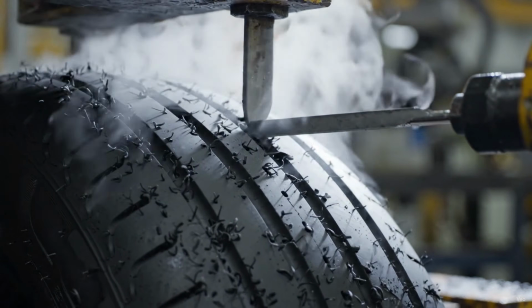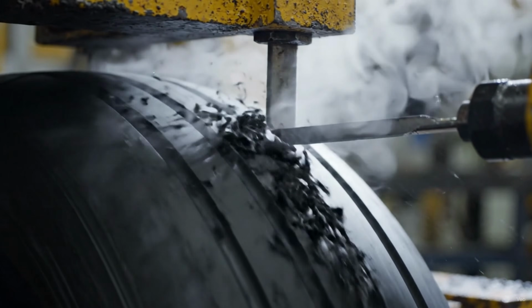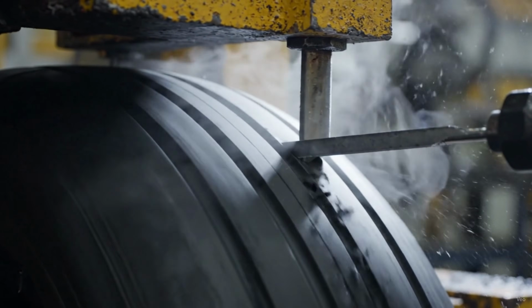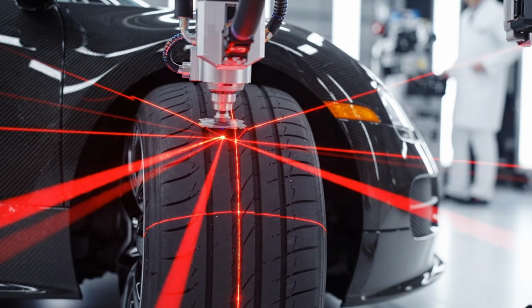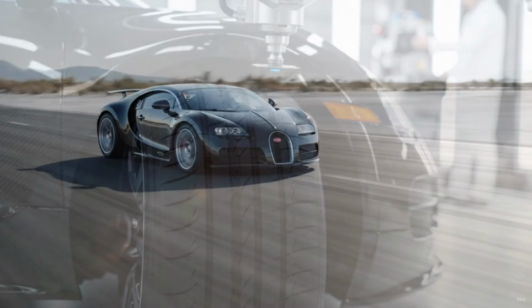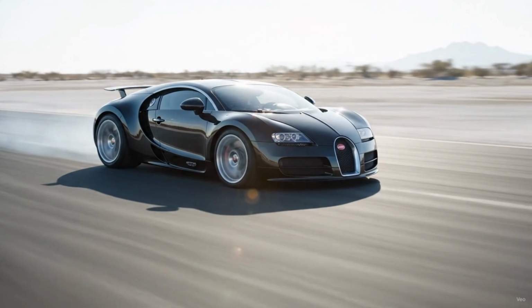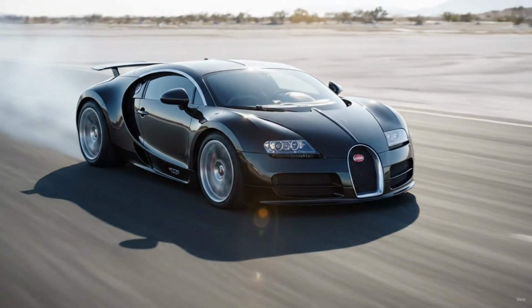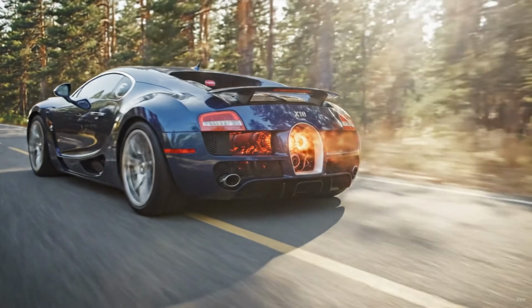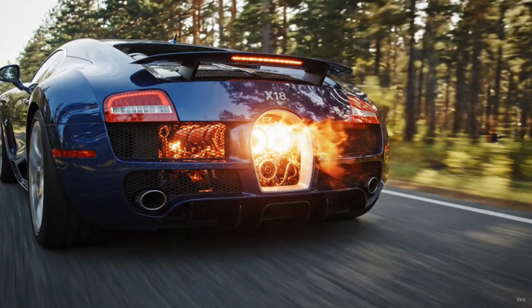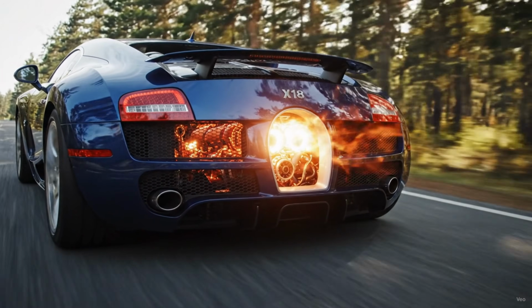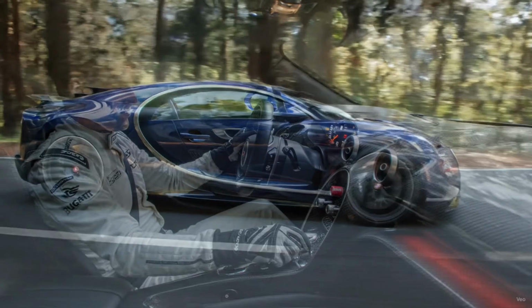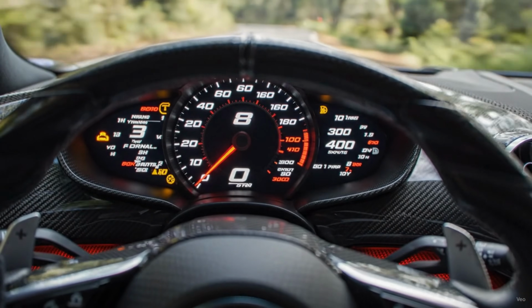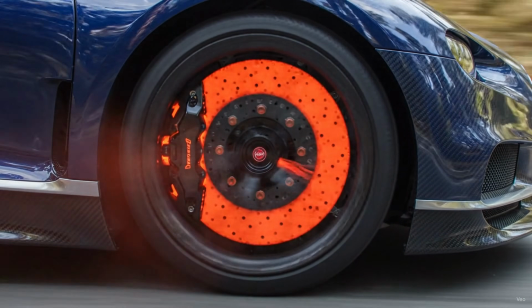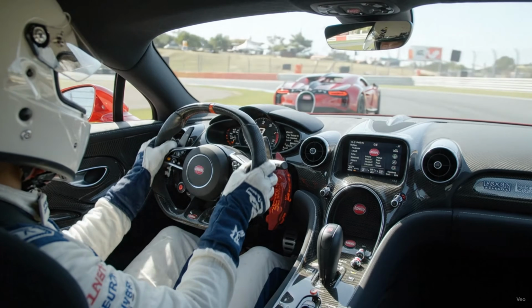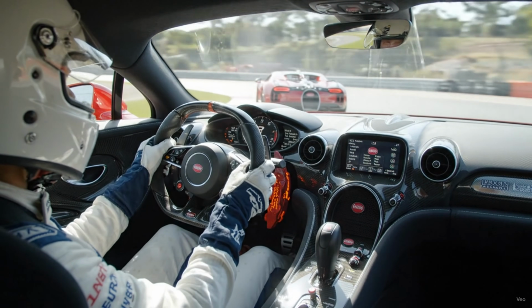Yet, even though vulcanization creates an exceptionally tough and flexible structure, it still cannot overcome the physical limits of extreme speed. Imagine paying $42,000 for a set of tires that can survive for only 15 minutes. That is the life or death limit faced by the Bugatti Veyron when it runs continuously at more than 400 kilometers per hour. At such terrifying speed, brutal friction generates enormous heat. And if even a single belt layer loses stability, the entire tire can tear itself apart in an instant.